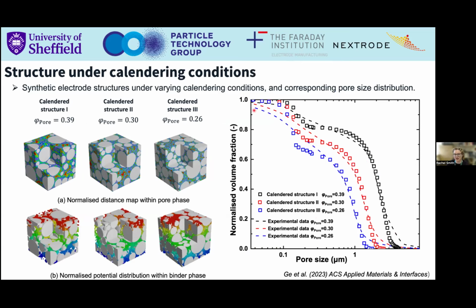experimental data here. So these dotted lines here, experimental data, and the simulation data are the squares. And what we attempted to do is create bimodal distributions, basically, of micropores and macropores. Now you can see that these aren't perfect replicates, basically, and what we're seeing here is that we're overestimating, I guess, the sharpness of these peaks in our simulations.